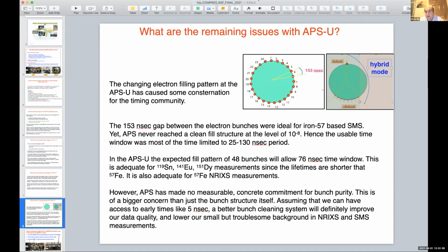Now, this makes it very hard for those of you who are doing nanosecond or picosecond time-resolved experiments. So this is an issue. The 153 nanosecond gap between the bunches was ideal for iron-57 and SMS. Yet, this 153 nanoseconds was not fully usable. APS never reached a clean fill structure, namely the bunches following this main bunch, and the 2 bunches before and 2 bunches after, each separated by 2.8 nanoseconds, were never clean.